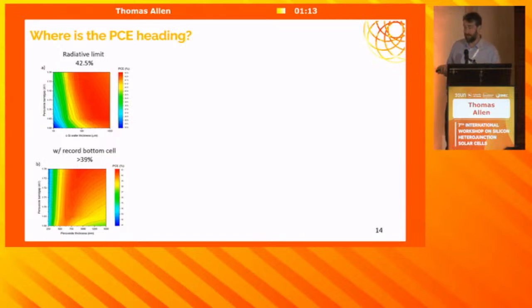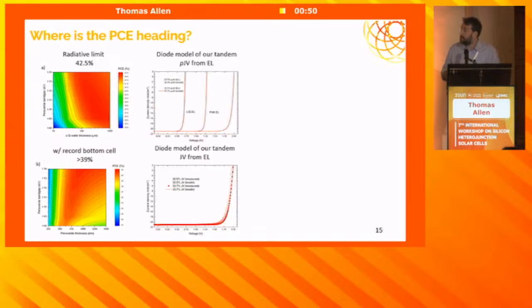If you limit yourself to a state-of-the-art silicon heterojunction bottom cell, our bottom cell is not state-of-the-art, unfortunately. But if you were to do that, you have only a very small efficiency penalty, and even if you limit yourself to reasonable band gaps, the radiative limit of the tandem cell is still over 39%.